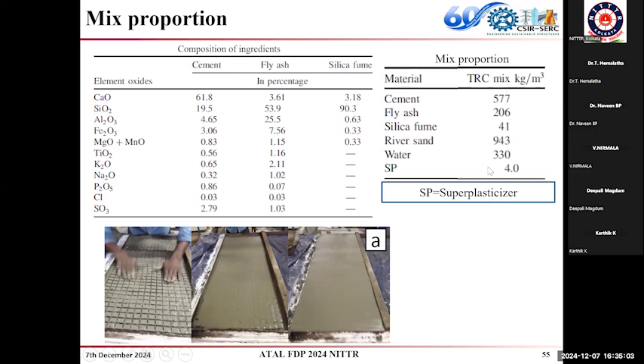Earlier it was using only the quartz powder or quartz sand, but nowadays, because it was very costly previously, the cost has now been reduced, because we have replaced that quartz powder and sand with river sand. So the number of layers depends upon the requirement: what tensile property we have, what flexural behavior we are expecting from this particular type of textile reinforcement. We can increase the thickness from 10 mm to 30 mm, 40 mm, whatever it is. And depending upon the requirement, we can keep one or more layers of the textile reinforcement.